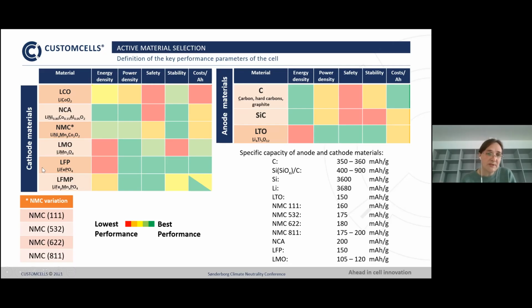But there are also other materials like the LFP. We have seen that in the previous talk. The LFP has a lower specific capacity in comparison to the NCM materials, but also a lower voltage. However, it is more stable because that's not an oxide, it's a phosphate. So the binding between phosphorus and oxygen is very strong, and therefore the stability of the material is higher, and we can gain high cycle stabilities. Also, costs are lower because there is no critical raw material inside.